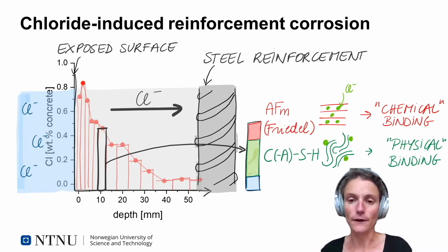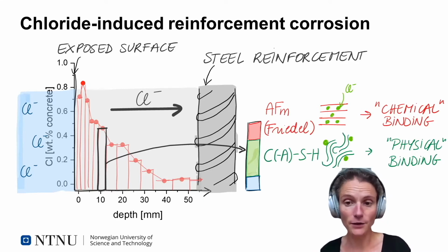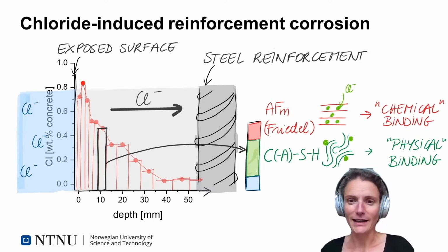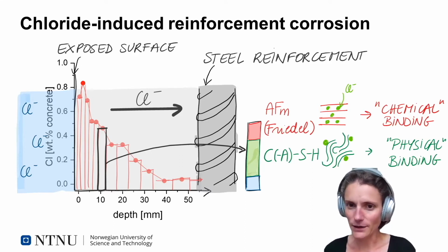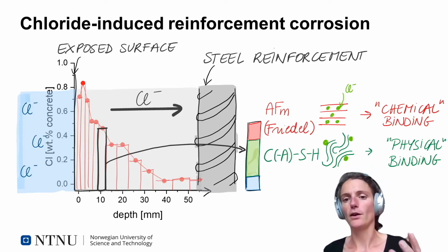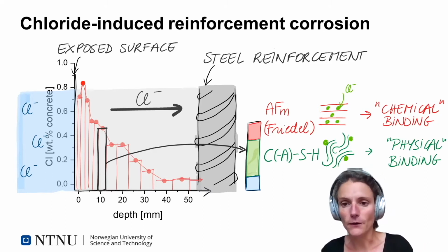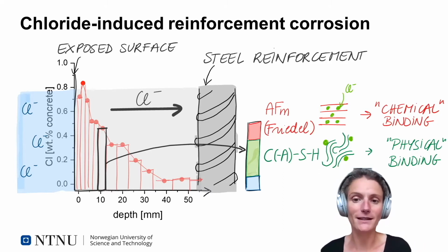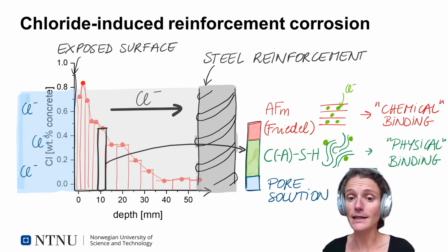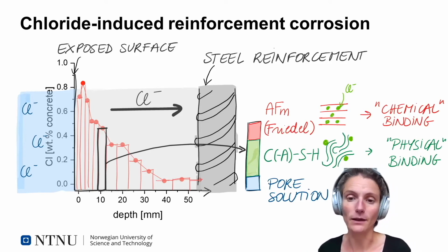In the case of calcium aluminate silicate hydrate, or in short, C-A-S-H, the chlorides are not really taken up in the structure, but they're more adsorbed or attracted by the surface. And this we refer to as physical binding. And finally, some of the chlorides will be found also in the pore solution, which we often call free chlorides.